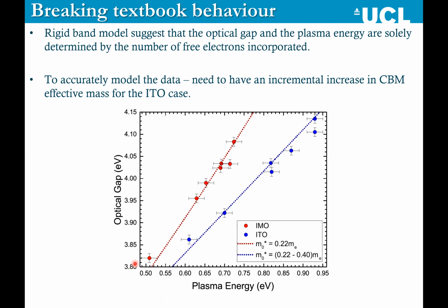But when he tried to fit the effective mass for the ITO films, he had to actually use an effective mass that incrementally increased from 0.22 to 0.40. So what this seems to say is that incorporation of molybdenum doesn't change the effective mass of your conduction band, but somehow incorporation of tin does. So this was definitely a new idea in the field.